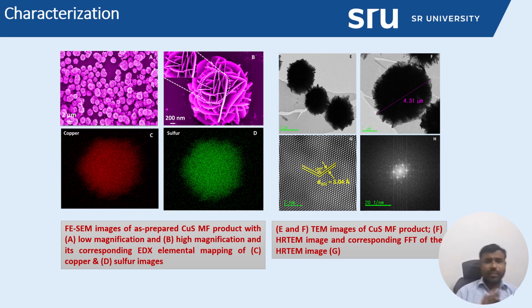Interestingly, the flower-like morphology is composed of several thin nanosheets. See here, in the high magnification image, we can see the thin layers of nanosheets assembled together to form the flower-like morphology. The thickness of the thin layer morphology we have estimated at around 15 to 20 nanometers. Overall, the cross section of the morphology was estimated to be around 2 to 2.5 micrometers.